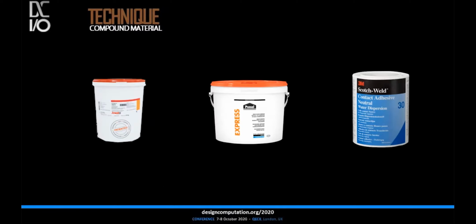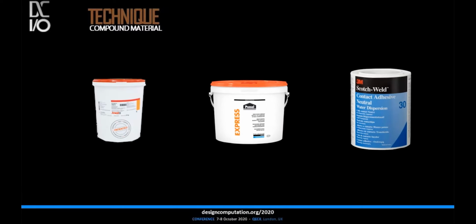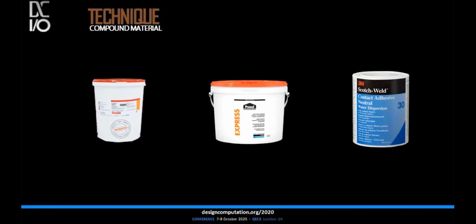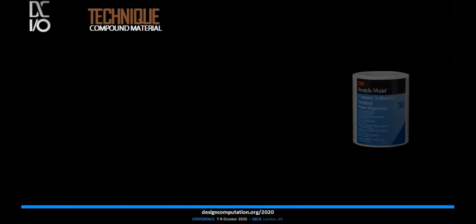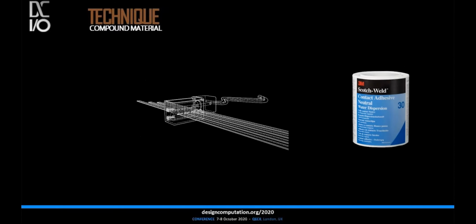For combining the willow filament strings in a fast additive manufacturing process, an adhesive system had to be chosen. Our method requires a fast drying and binding time at an affordable price. As the material itself can be manufactured inexpensively, suitable adhesives should be equivalently economic. Several adhesives, such as white glues, UV resins, and contact adhesives, were tested. With several contact adhesives, we laminated the filament strings and left them to dry for 24 hours.